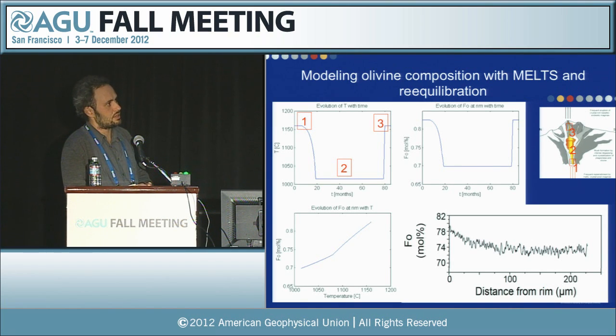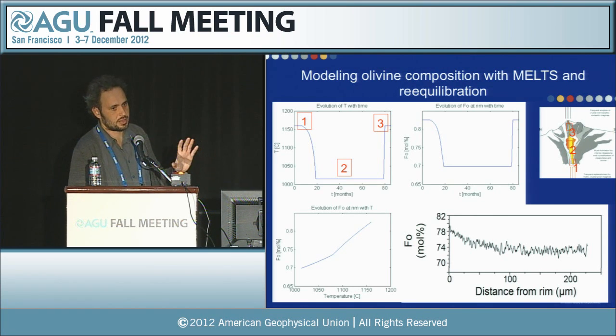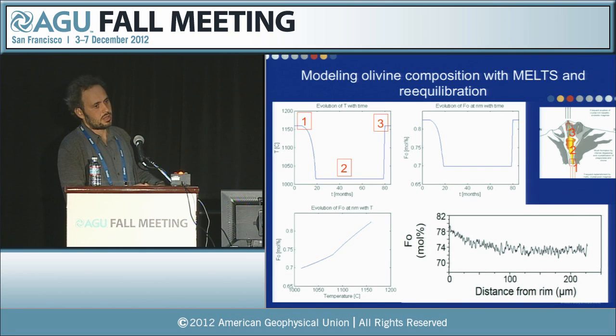So again, you remember this simple scheme, 1, 2, 3. Here we have 1, the arrival of this mafic magma. This mafic magma quenches, and it stays at a given lower temperature. Then before eruption, there's a replenishment, and the temperature rises. This is a time-temperature plot, which I agree is arbitrary to some extent, but I think the 3 steps, sort of hot, cooler, and hot again, is robust. From here we can calculate the olivine in equilibrium. If we go at this temperature, this would be the olivine in equilibrium, and we think it's this plateau.